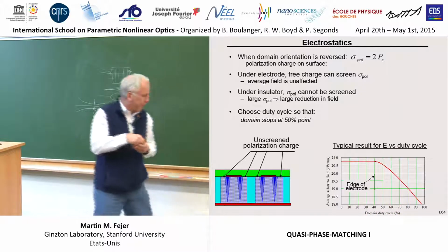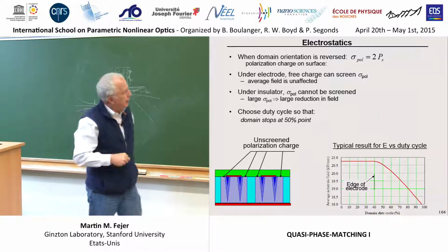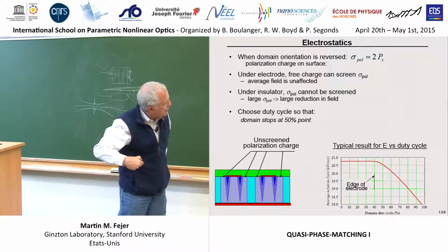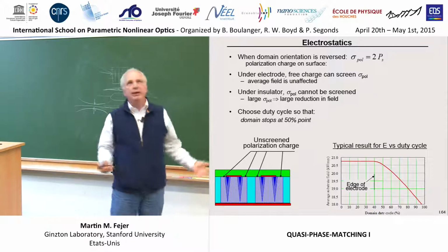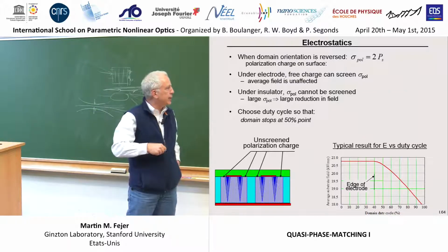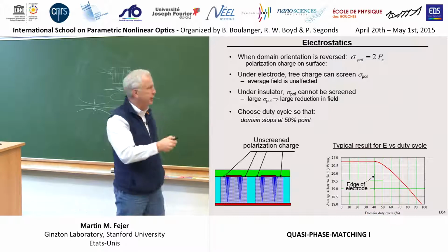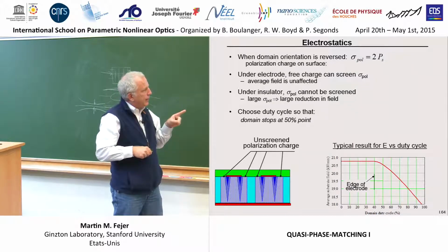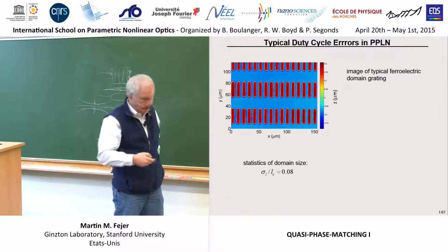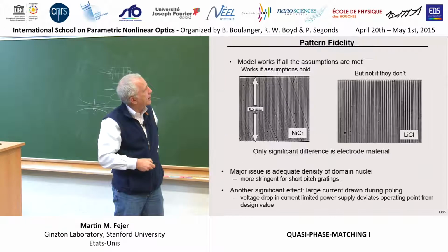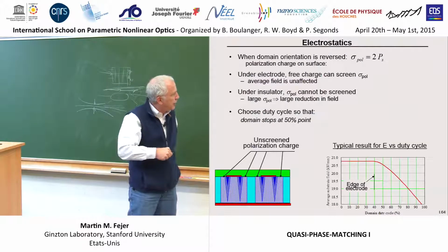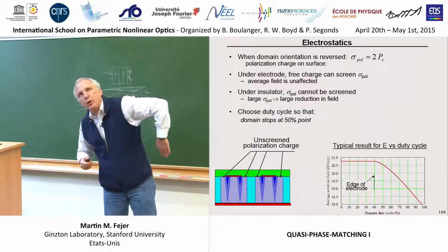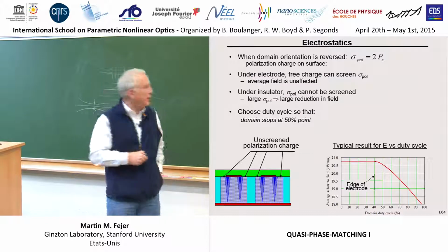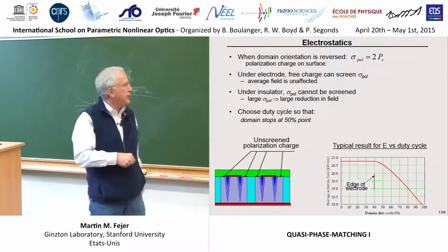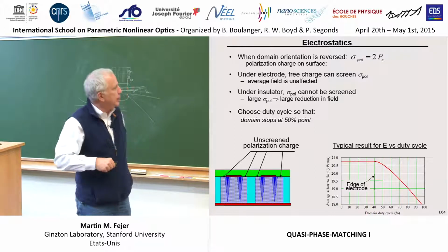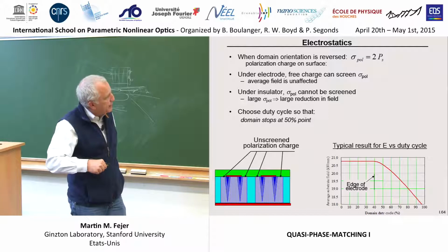initially, if you put a large enough field on here, the domains will start to grow. Once they start to grow past the edge of this electrode and underneath the insulator, you can no longer supply charge to this surface, right? This is connected to your power supply, so you're dumping charge there as much as you need. But out here, it's insulated, and so as the domain moves under the insulator, when you flip this dipole, you have a surface charge that's twice the spontaneous polarization forming here, and you can't screen it out because there's an insulator on top.